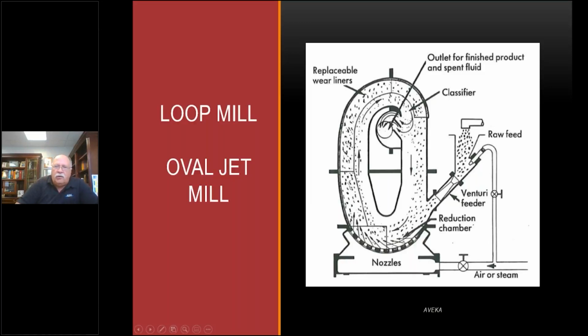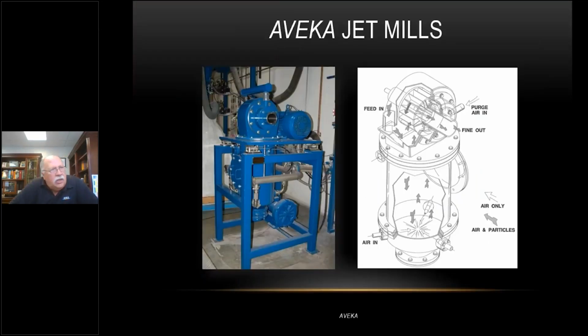So let's show you the schematic of a fluidized bed jet mill, and this is what we're going to be talking about today. AVEKA makes these mills. We sell these mills along with the classifiers that go with them. Basically you have a grinding chamber down at the bottom where, in our case, we have 3 high pressure jets blowing into the system. The particles are loaded into this fluidized bed. They're grinding in this area. When they get small enough, they're air entrained up to the top, and they go through this classifier, basically this rotating wheel up here. The smaller particles will go through, and at higher rotational speed of the classifier, the bigger particles get pushed back down to be ground up. So basically what you're doing is removing the product, the fines, out of the system as fast as you can. This allows us to get a tighter cut and better utilization of the material.